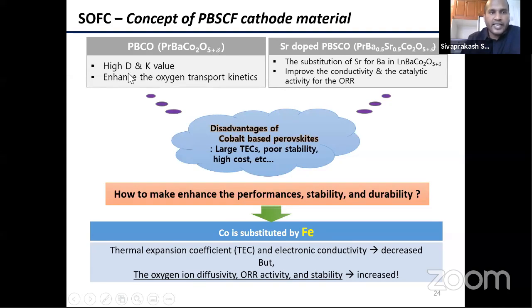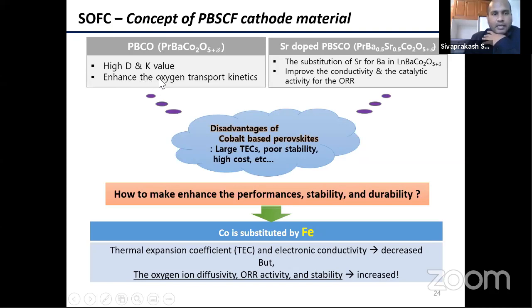This material shows high oxygen diffusion and surface exchange coefficient, D and K. D is the oxygen diffusion, K is the surface exchange coefficient. It has high oxygen transport kinetics.